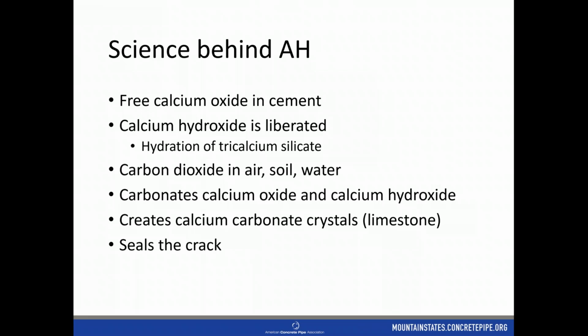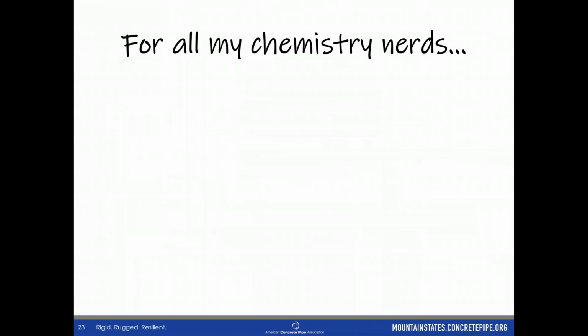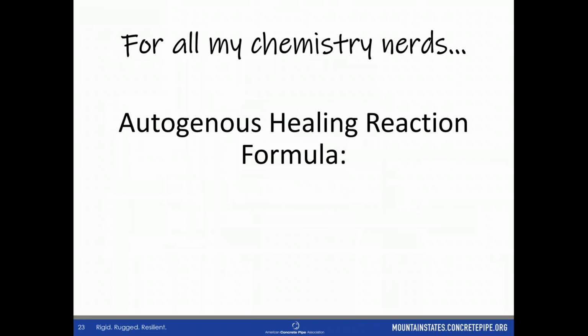So people say, well, I'm concerned about this crack because if water gets in there and it corrodes the steel, then it's going to rust out. It's going to pop out the pipe there, and it's going to cause major issues with rust and corrosion. And this autogenous healing actually prevents that from happening because it seals that crack, and it doesn't allow the water to get in there to touch the steel. So it's really fascinating.